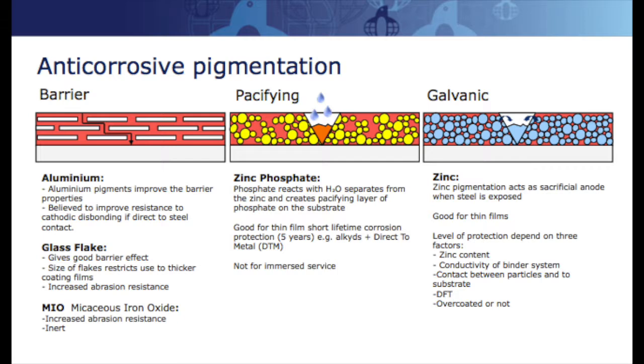In the middle there, you see something called passivating pigments. And those pigments worry me. They worry me, zinc phosphate especially. And the reason I put zinc phosphate up there is because I want to give a word of warning. Zinc phosphates will give you a very good passivation of any damage for a short period of time, which is very interesting when we're doing testing.